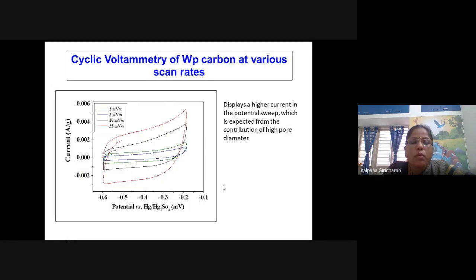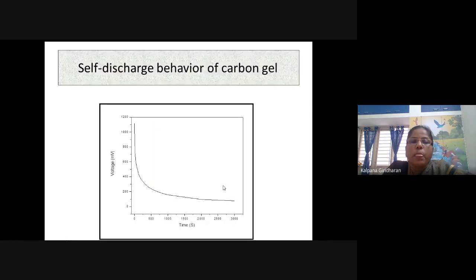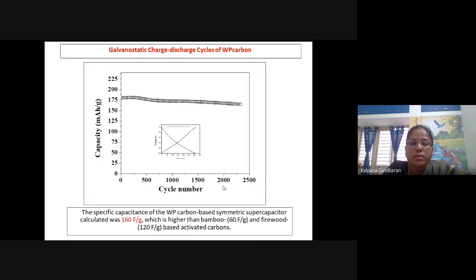We have also obtained an almost rectangular type cyclic voltammetry at different scan rates, showing a high current in the potential sweep, and the self discharge is very minimum. This specific capacitance of 160 farads per gram is calculated from CV, and the galvanostatic capacity is also almost stable even up to 2,500 cycles.